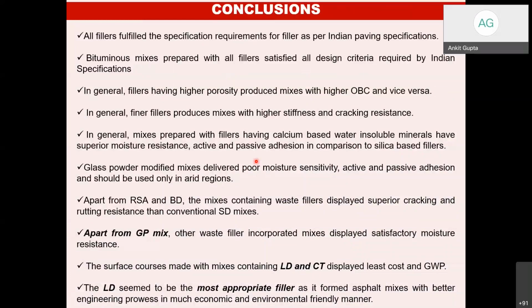Normally, the fillers having higher porosity produce mixes with higher bitumen content. Okay, so if a higher porosity is there, which is normally the case with rice straw ash and the finer fillers, they use some higher bitumen. Okay, so that is again not a good sign in terms of cost economics. In general, the finer fillers produce mixes with higher stiffness and cracking resistance. So the finer the filler, the more compact our structure is.